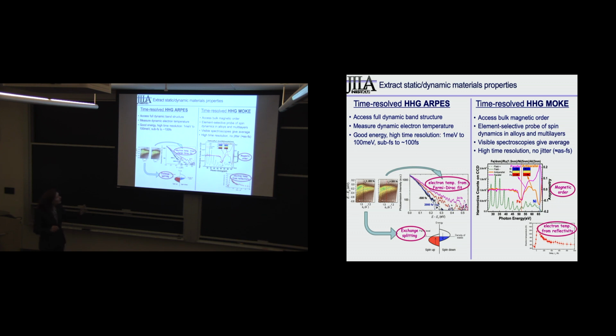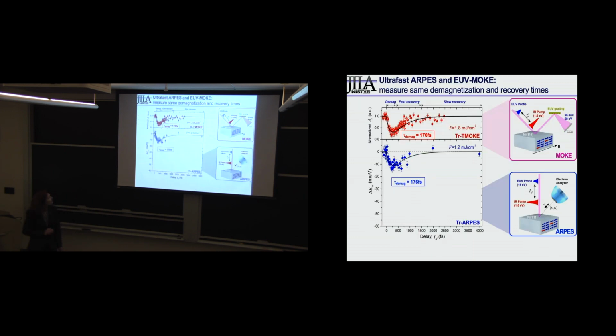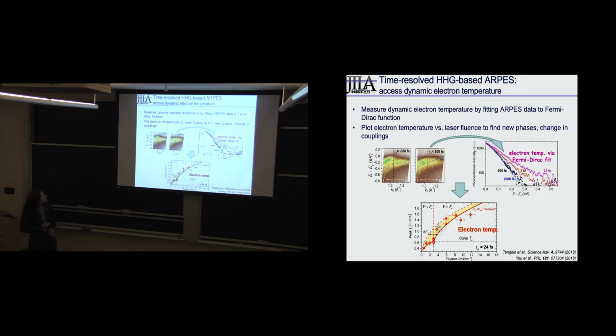So initially this was done as just a survey. Do we know what we're measuring? It was just done on nickel, we didn't expect to see anything new. And we were very happy that the demagnetization curves I showed you earlier looked the same with both spectroscopies. That was nice because we didn't know that was going to be true. But then we started looking at the photoemission data more carefully. What we did was plot the electron temperature, by looking at the Fermi edge, as a function of laser fluence. So that's what's plotted here.